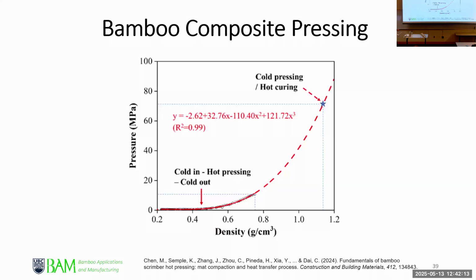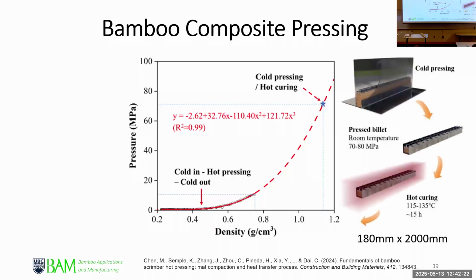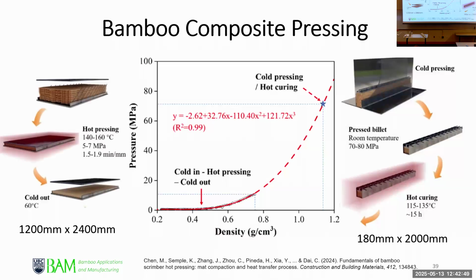On the pressing side, this will last a bit. So when it comes to manufacturing engineered bamboo product, pressing is critical because bamboo is so hard. It requires a lot of pressure. In the first version of bamboo timber or the hard bamboo floor that you see, they actually made it with very small size. You can see the size is very narrow, although it's a bit long. But because the pressure required is so high, there's a second generation of manufacturing process where heat is introduced. And that allows you to make a more panelized product, with heat helping the consolidation.